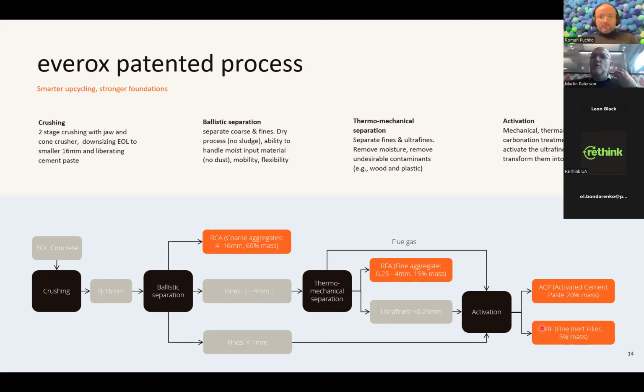But again, our main focus is on cleaning up the cement paste, getting the silica out of that, and then we're basically using the CO2 coming from the flue gas of the thermomechanical separation, so our own internal CO2 source, to carbonate the material. And that's what comes out of that, the activated cement paste. And I will explain afterwards a little bit about the quality of that material.